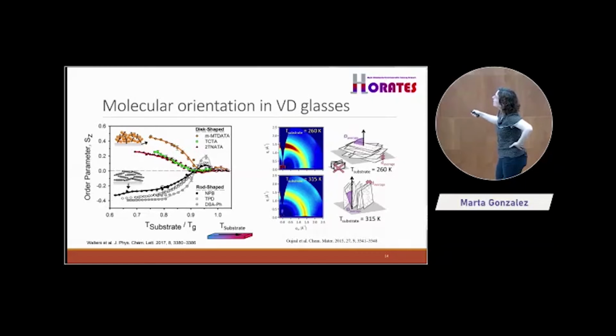So you see that here, depending, and you say, yeah, but this is not going down, as you were saying, no? This is not parallel. Yeah, but it depends on the shape of the molecule. If the molecule is like a rod, okay, it will tend to lay flat. If the molecule is more like a disc, it tends also to be flat. However, what we are measuring here is the orientation of the dipole, and the dipole is up, okay?